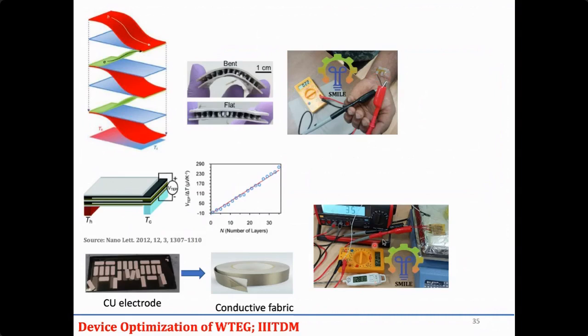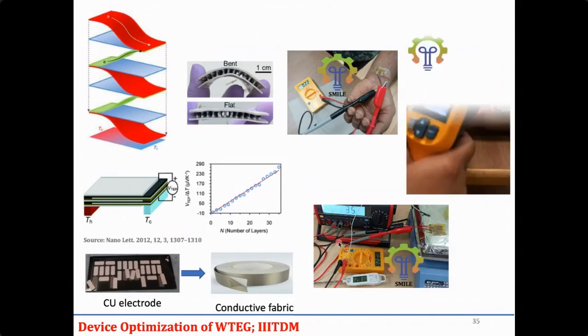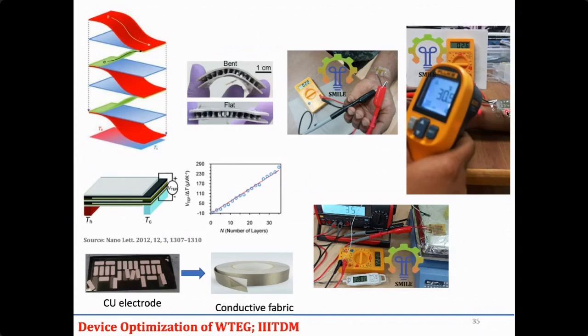And we wanted to make sure about the difference in temperature, so we made a hot plate, like an induction stove. The hot plate temperature is 35 degrees, and we kept room temperature at 28 degrees, and the difference is almost 7 degrees. With the 7 degree difference we can see 2.8 millivolt was generated. So the power increases whenever the delta T is increased. And here we can see another device with a different material, which generated 2.6 millivolt from the body heat. So from the body heat, the power can be generated, which is really used for IoT device applications.